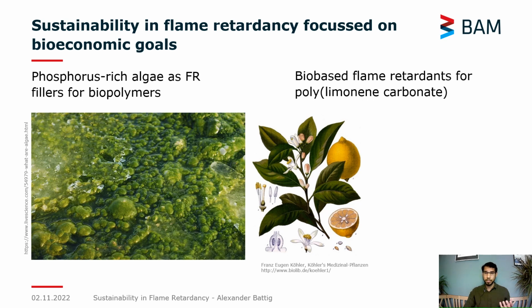So if you don't know what polylimonene carbonate is yet, it's a type of polymer that's based on limonene, and limonene is a compound that is extracted from lemons, and the production of polylimonene carbonate actually consumes carbon dioxide. This is done with a catalyst, but it's done at room temperature at 24 degrees, but at 25 bars. But it is technically possible to create this material. It's a bio-based material. It has some unique material properties, and investigating the flame retardancy of this material is one of our new topics.